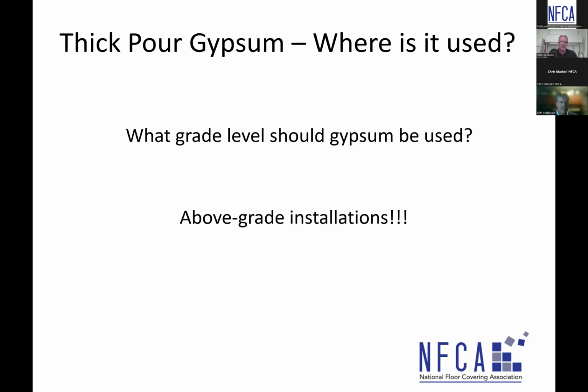If we do get the gypsum saturated, it has a little bit of a lower pH material, and things can grow on the gypsum. So it's very common with these products, which is why you've got to follow manufacturer's recommendations, but generally speaking, these products are above grade applications where we're not dealing with ground moisture coming into the installation.